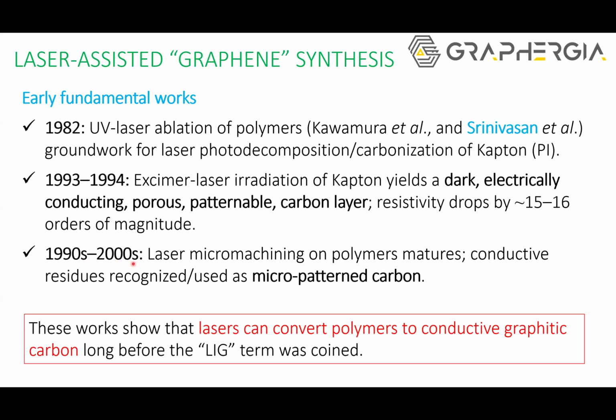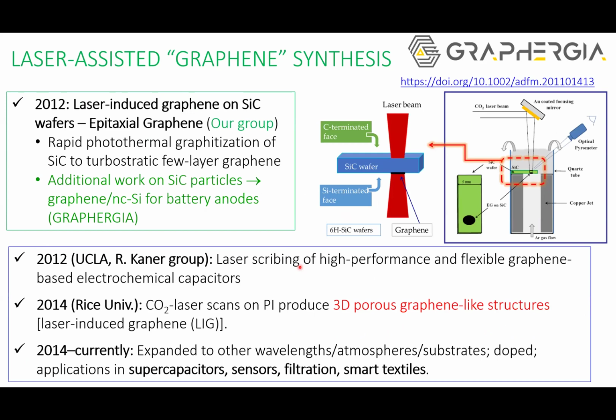Between the 90s and 2000, also the laser-based micromachining of polymers was further developed, and research groups were able to prepare micro-patterned carbon for various applications, not so much related to energy, but mainly to electronics. At about 2012, in our group, we started working with the use of lasers to produce graphene, having worked at that time with silicon carbide wafers, preparing what is called epitaxial graphene, a form of flat graphene useful for microelectronics, using a CO2 laser beam, working at ambient conditions.